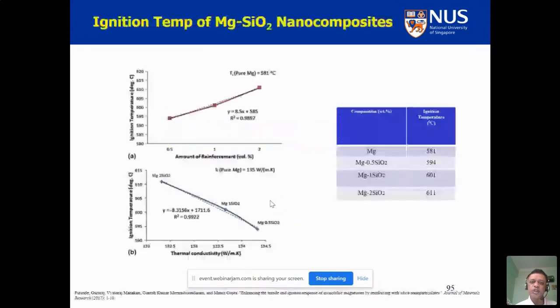Such kinds of bubble charts are available in the open literature. Now, there's a big misconception about the ignition temperature of magnesium. As I indicated, the ignition temperature of magnesium is approximately 580 degrees centigrade. And if you put in nano reinforcement such as SiO2, then the ignition temperature increases. Why does the ignition temperature increase? The only theory that we have is that it reduces the thermal conductivity, and if you reduce the thermal conductivity of the material due to the presence of nano reinforcement, the ignition temperature goes up. Of course, we are still working to find out if there is any other mechanism which leads to the increase in the ignition temperature as a result of the presence of nano reinforcement.